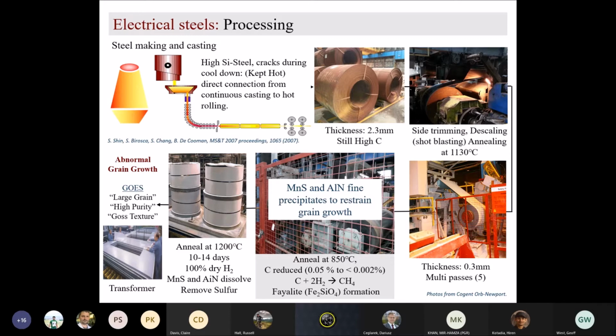Now at that stage, the aluminum nitride and manganese sulfide will be dissolved at that temperature, and then the grain boundary will be free from them, and then abnormal grain growth will happen, and you'll have very large grains, high purity, because there is no carbon, no aluminum nitride and no manganese sulfide precipitate, and you have a Goss. Hopefully, you will have a Goss texture to be used in transformers. Okay, next.